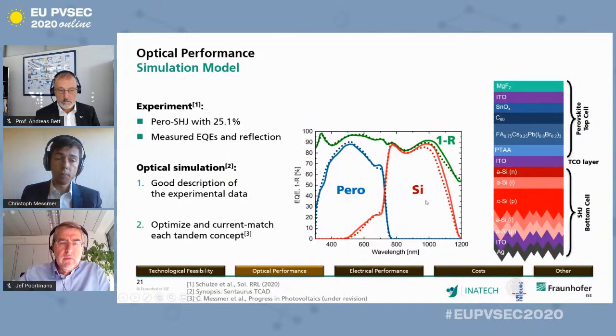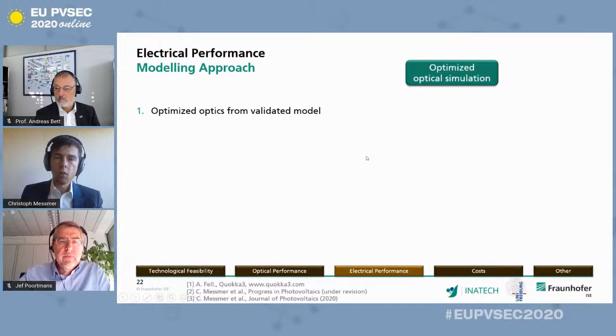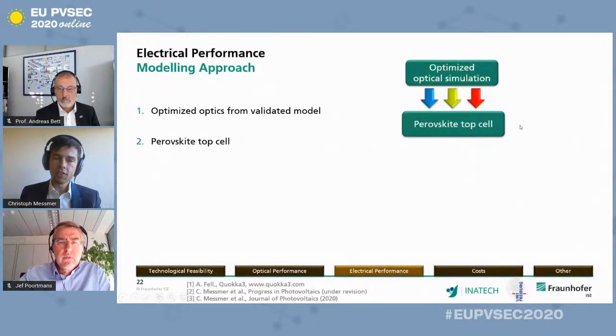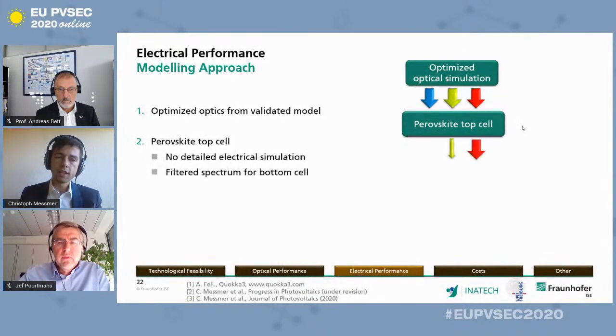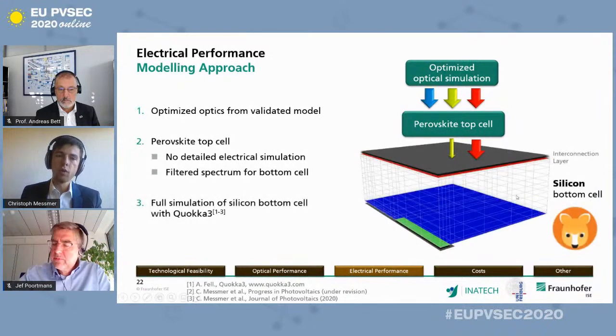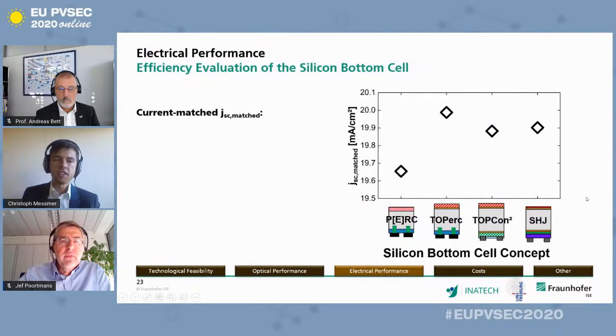And in the second step, we optimized and current matched each tandem concept for the industrial realization. And with this, we move on to the electrical performance, where our modeling approach was to take the optimized optics from the validated model and pass it through a very simple perovskite top cell model, where we had no detailed electrical simulation, but we had this for a filtered spectrum for the bottom cell, for which we then did a full simulation with the Quokka 3 simulation tool. And this leads me to the first results of this study.